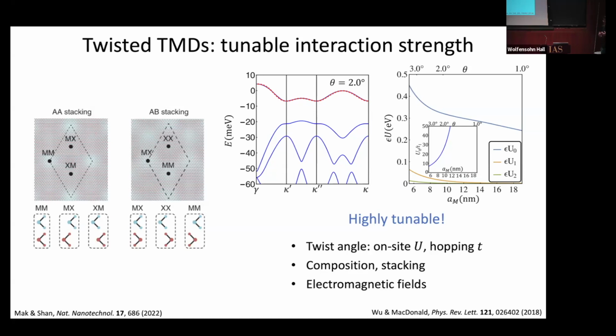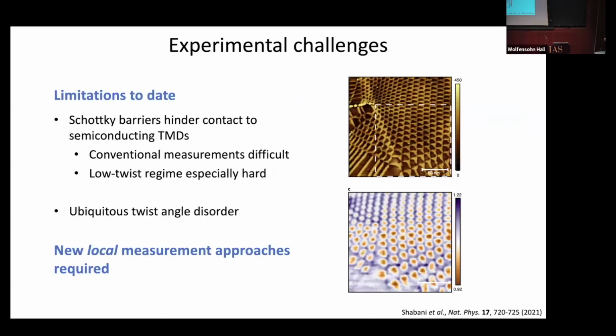And so you can hope, at least by exploring different twist angles, to map out different regimes of this effective long-range Hubbard model that you have. And beyond that, as you change from material to material, as you change the composition, the starting point, the stacking, as I described, all of these things can have profound effects on the physics that comes out. And in many cases, as I'll show you, by applying electric fields or magnetic fields and tuning carrier density, you can change the nature of the states that come out. So these are really a nice model system to explore.